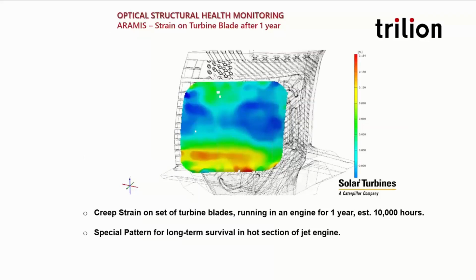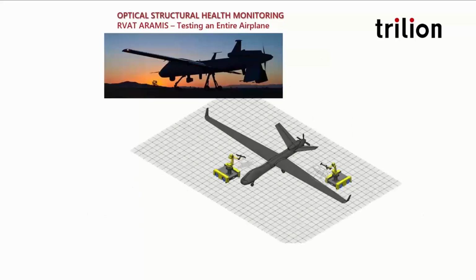And in this case, we see the CAD brought in and the strain at the base of a turbine blade. And this turbine blade was patterned with a ceramic pattern and put in a jet engine for 10,000 hours, a year of operation. And this is the creep strain from the blade. Truly impossible measurement, but this was done and is now done on each new design. It invalidated one of their computer models and validated another one. And so now their products are just hugely more accurate than they used to be.